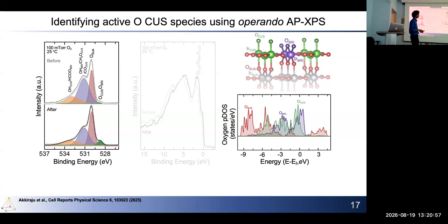Here's the oxygen density of states that we computed, and we see that close to the Fermi edge at close to 0, there is a spike of oxygen CUS species. So this is where we started to think, could this be a signature fingerprint of the oxygen CUS species.